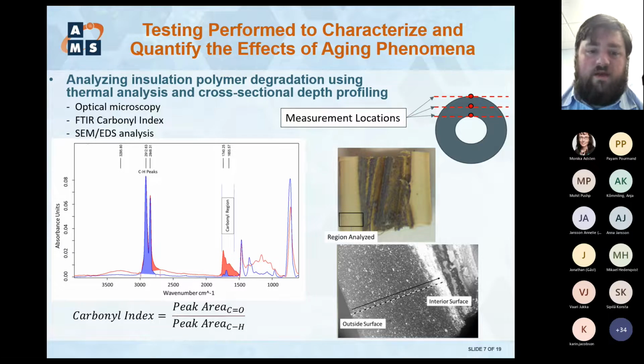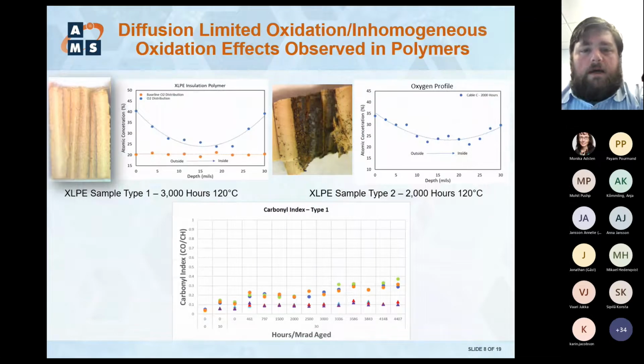And then we also, like I said, employ SEM EDS analysis. That's what we see in the bottom screen. That's just an SEM image, but we actually go through the cross section of the insulation and look at the distribution of different elements in the material. And so I'm going to get into the types of things we've seen in our data, which wasn't really surprising given the temperatures we're at in a lot of cases, especially with diffusion limit oxidation and inhomogeneous aging effects.